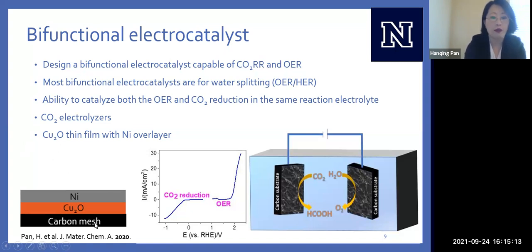And so the catalyst that we're making today is a thin film catalyst. So we start with carbon mesh. Basically, this is carbon paper. So just envision a piece of paper, instead it's made out of carbon. And using electrodeposition, we can deposit a thin layer of copper oxide and a thin layer of nickel on top of that. And the idea is that if we can tune the thickness of nickel, we can control products. And I'll point out here that this is not an alloy. These are just layers on top of one another.